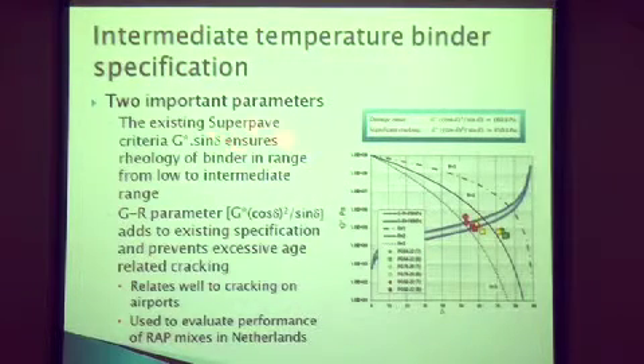This is what we call the G-R parameter. In the intermediate temperature, we have this existing Superpave parameter, G* sine delta, and this gives us information related to fatigue. And this really is dependent upon the rheology of the binder in the range of low to intermediate. So you go from low temperature to intermediate temperature. This G* times sine delta really ensures that rheology is correct in that range. This other parameter, G* cosine squared divided by sine, makes sure that you do not get excessive cracking.